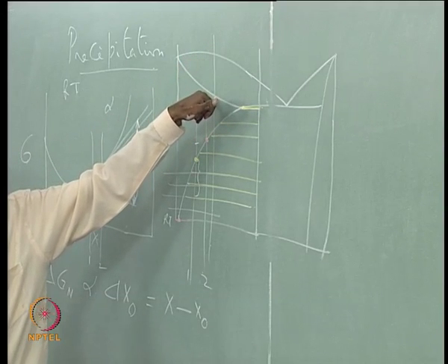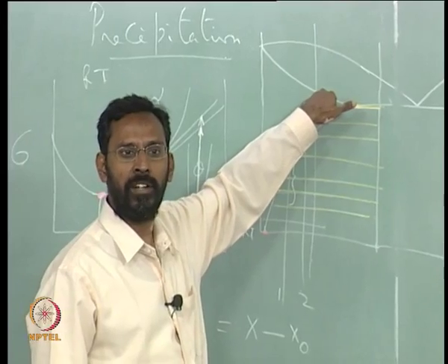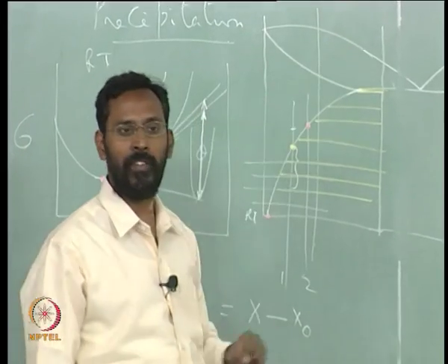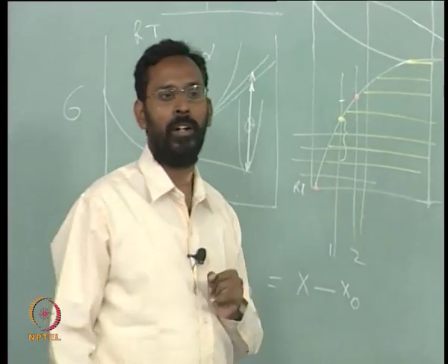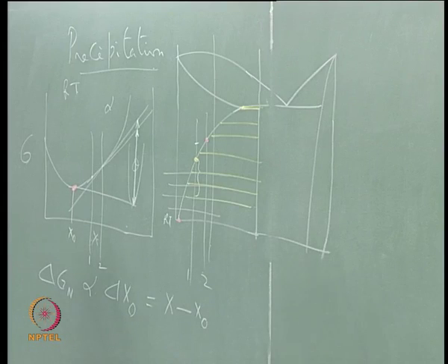In this case, you see that this alloy solidifies completely as single phase alpha. Am I right? Solidification is only single phase alpha, there is no eutectic there, and as I am cooling this alpha to room temperature, it starts precipitating the theta, and that theta comes out at the grain boundaries.